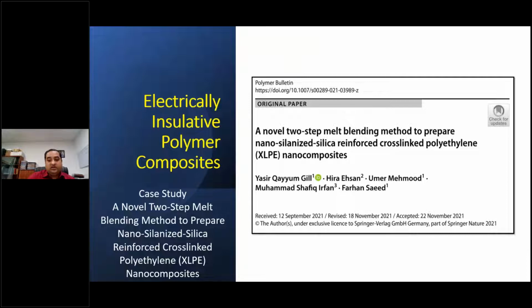Also, UV degradation analysis of the samples was carried out, and the overall results showed that the incorporation of filler resulted in formation of a networking domain between nano-silanized silica and polymer matrix. Silane groups, which were coated onto the silanized silica, gave better compatibilization that resulted in better resistance to UV degradation, so your product can be utilized for a longer period of time.